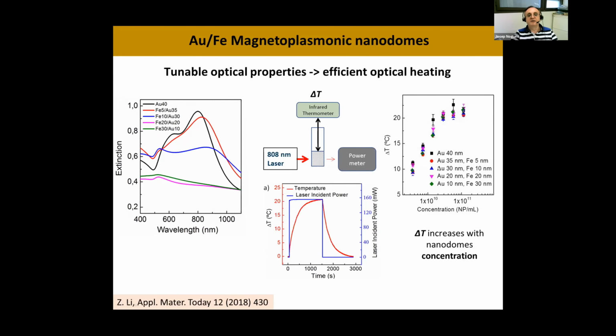Also, the heating ability of the particles depends on the concentration, as expected, and we see that for higher concentration it tends to saturate. This is because at higher concentration the nanoparticles absorb so much light that the light does not reach the last particles. So eventually only the first part of the particles heat, so that's why there is a saturation. And also interestingly, the heating properties are quite independent of the iron content.